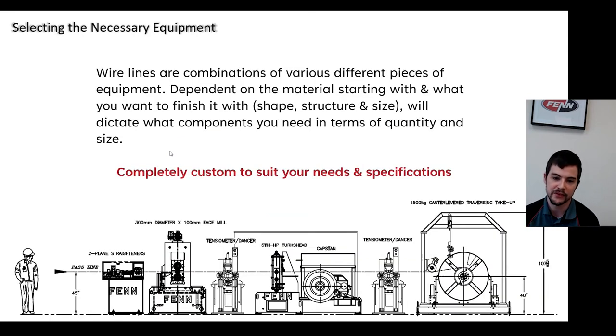So this is just, as alluded to in all those photos, the combinations change dramatically depending on your size and needs. This is just to give you one visual example of a line we did in the past. We ran a two-plane straightener for basically knocking out cast and helix in the wire. We used a single mill for taking the round wire and knocking it into a natural edge flat.